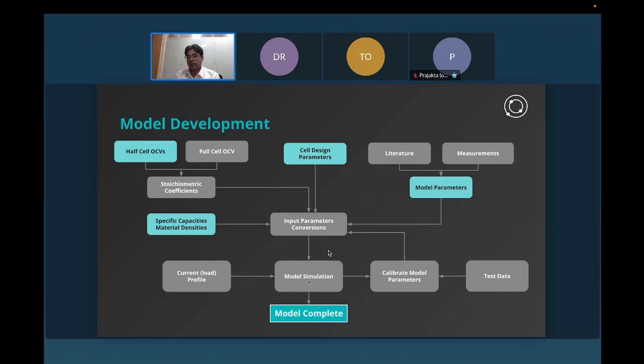Now, in the beginning, because the model parameters are not known, we will never be able to use these models and get the exact voltage response for the cells that we are going to model. And that is where calibration of these model parameters becomes important, and for which you would need first the test data. You will start by assuming certain model parameters, you compare your response with the test data, and then start iterating over the model parameters, making sure that it is matching your test data. In this particular case, we have HPPC data as the test data to complete this model.